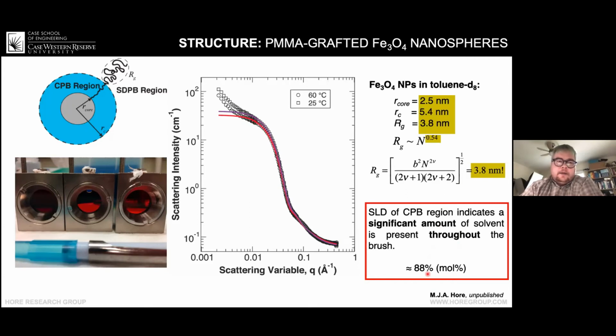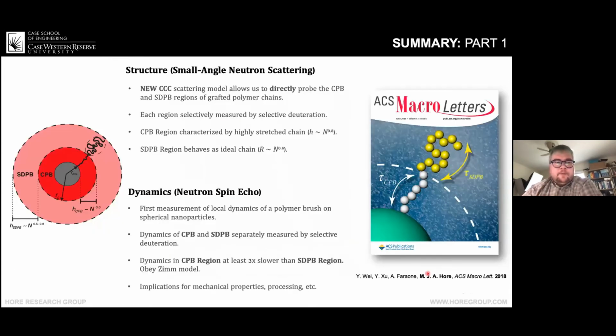So it's to say that perhaps it's not surprising that we can apply the Zimm model so nicely, even in the concentrated brush region where there's a large amount of monomers. So to summarize this first part of the talk, we did 2 things. We looked at the structure of grafted polymer chains, specifically on spherical nanoparticles. We developed a new model that I only showed you schematically, but it allowed us to directly probe the 2 different regions of the polymer brush. And we highlighted the scattering from each of those regions by selectively deuterating them.